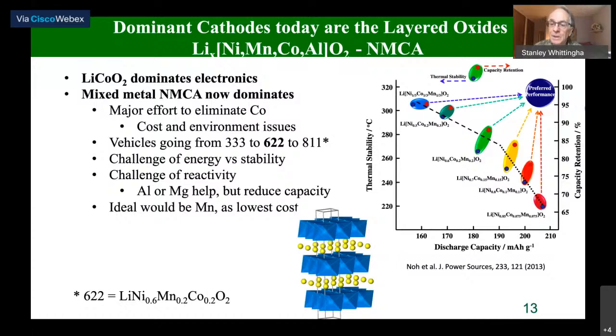And the higher the nickel, the worse this is. So we have to solve this. One of the ways of doing it is to put a little aluminum in there, which stops all the lithium coming out. It helps stabilize it. You can use magnesium to a certain extent, but it doesn't solve the whole problem. Nickel and cobalt are still expensive.